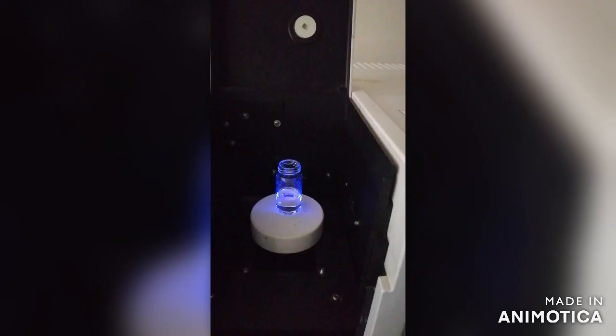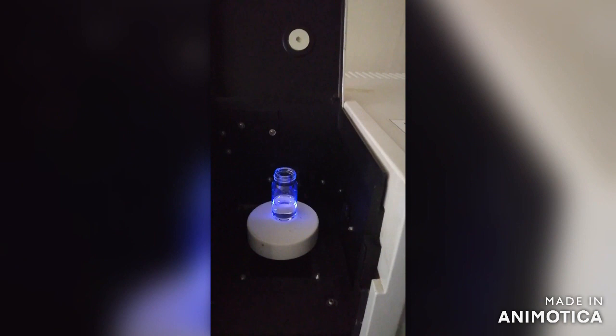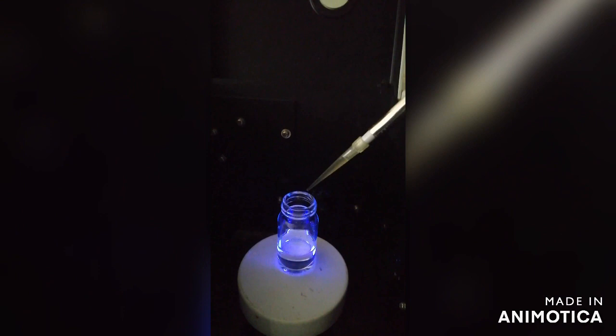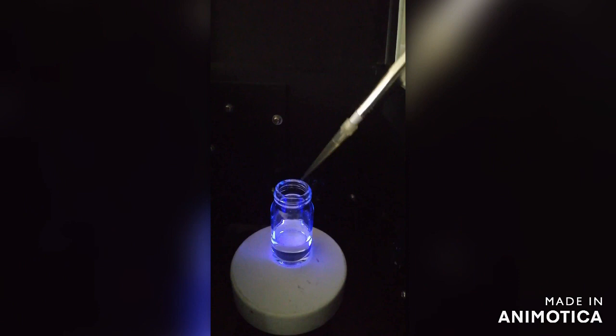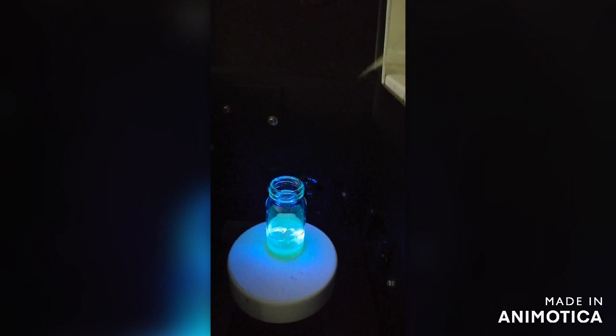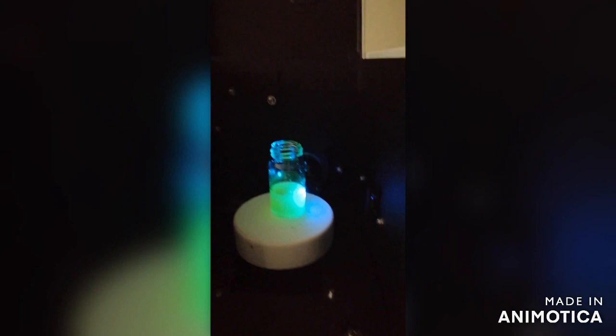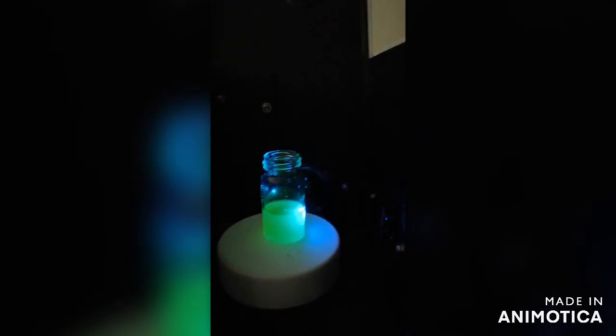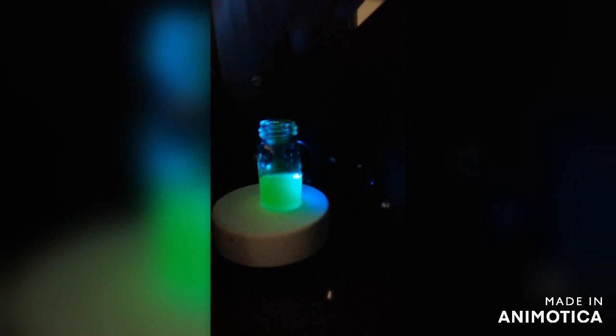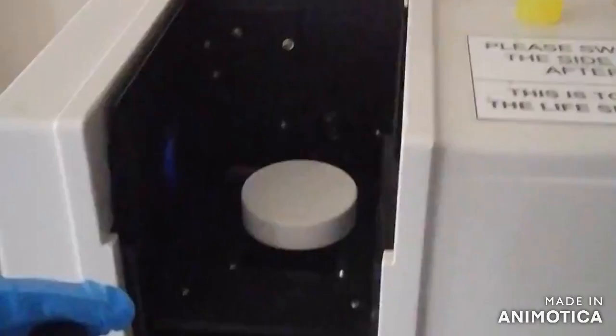Here, as we know, the perovskite constituent ions are much less soluble in non-polar solvents such as toluene. As we inject the DMF precursor solution into this toluene plus ligand solution, a sudden burst of nuclei starts and the crystallization of perovskite happens. And in the presence of ligand here, the crystallization stops at a certain point, which prevents further growth of the particle size. And these nanocrystals look extremely luminescent under the UV lamp.